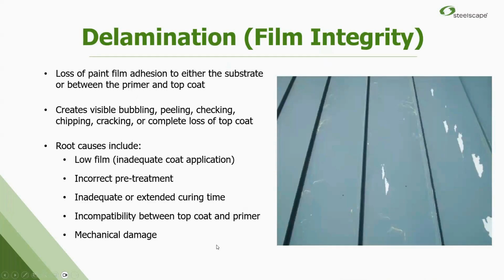Delamination or loss of film integrity. This is a tough one out in the field because there's so many reasons why this might happen. But it's loss of the paint, the entire paint system to the substrate. It may be loss of adhesion between the top coat and the primer for some reason. It may present as bubbling of the paint. It may be peeling like this. Chipping, cracking can present a lot of different ways.